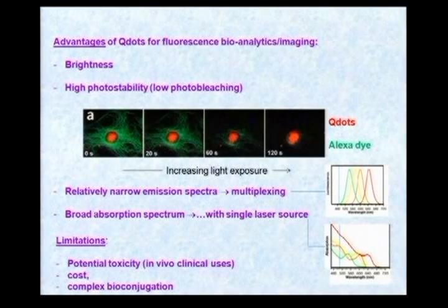And as a function of light exposure, you see, in fact, that the dye just bleaches away, whereas the quantum dots actually maintain their brightness. Sometimes they can even get brighter with light exposure. So this is very nice if you want to do long-term tracking, long-term following of cellular processes. You can use quantum dots for that purpose. They have relatively narrow emission spectra. As I said, this allows you to do multiplexing.